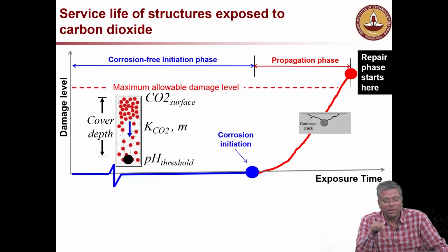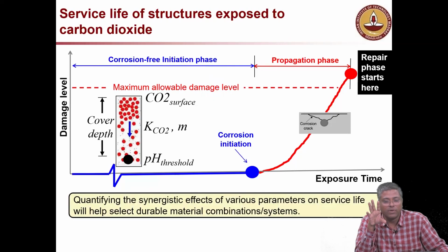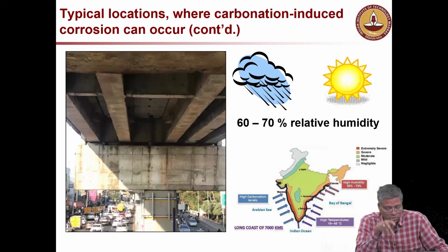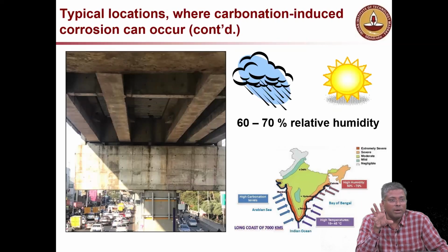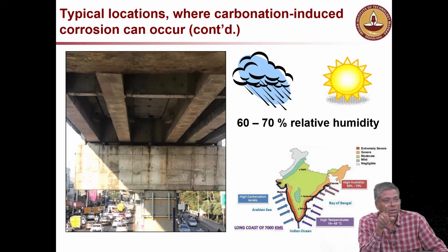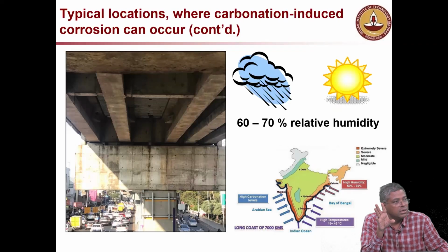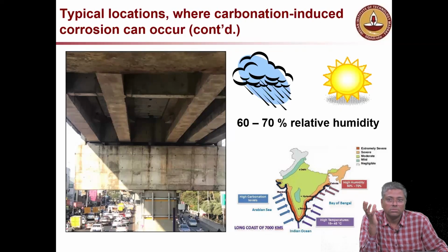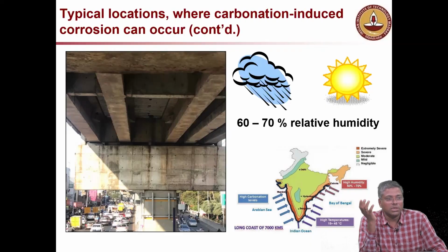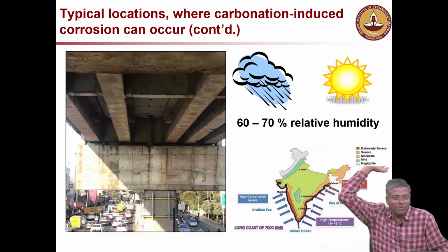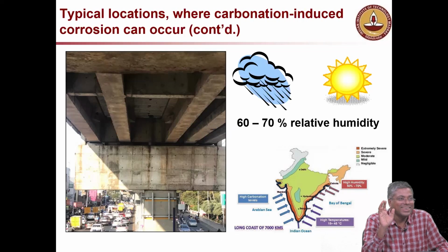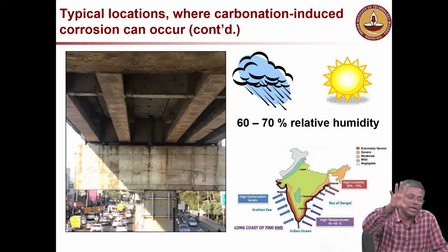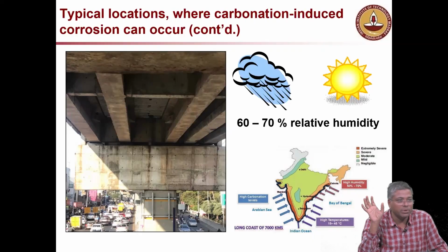Similar to the way we talked about service life, in the case of carbonation it is the pH threshold. This slide I also discussed a little bit. Imagine all the cars over there are pumping CO2 out, so the immediate surface of the concrete elements over there is rich in CO2. Atmospheric CO2 of 0.03 to 0.04% is far away from the city. Right here, if you go and measure, you will see very high, close to 1000 ppm. We have done that measurement.